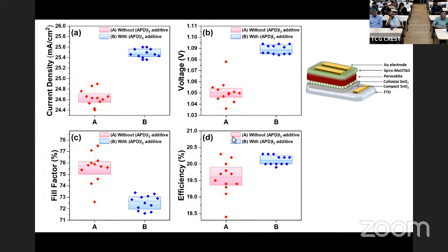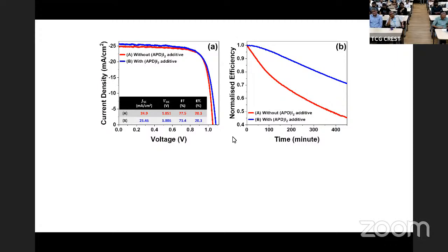But the main motivation was to make it more stable, and that is shown over here. Normalized efficiency as a function of time. If I don't use the ligand, in this particular case, it decays that rapidly, whereas if I use the APD molecule, then it's a lot more stable.